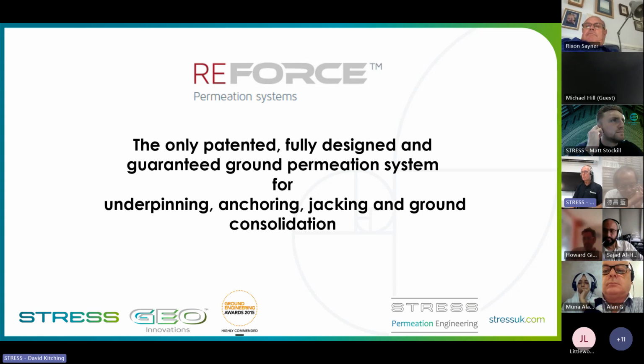We've also used these piles for jacking loads off, so you can mechanically jack loads off them. You've got this sitting out the top of the composite material. We've got heads that you put on that, and you can actually jack slabs back into position, and then put a cheap cementitious grout underneath it. And ground consolidation. Now, this is really interesting. For those of you who deal particularly with party walls and temporary works, basements are a bit of a nightmare.